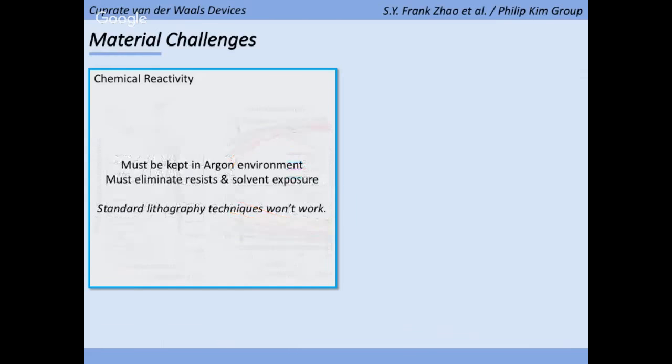So the upshot is that we have to do all the fab in an argon environment, and we have to eliminate all the resists and solvents that we use. Basically, as soon as you start developing your PMMA, your sample just dies in the developer solution. So these standard lithography techniques just won't work. But so far, all is not lost.